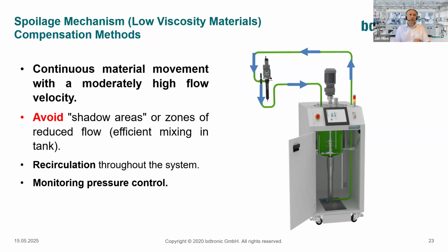Second, it's very important that you recirculate the material. As you can see in the picture on the right-hand side, we transport the material from the feed pump, which is directly underneath the vessel, into a hosing system which feeds the material directly to the dispensing pump. We feed more material to the dispensing pump than we need, so that we have a constant flow of material. The material consumed by the dispensing pump gets injected into parts, but most of the material gets transported back to the tank itself, so that you have a closed loop in the complete system, with a movement of the material so that this mechanism of sedimentation is avoided.